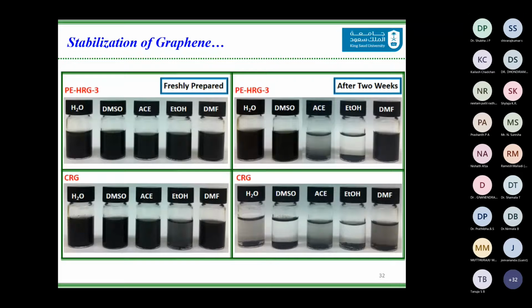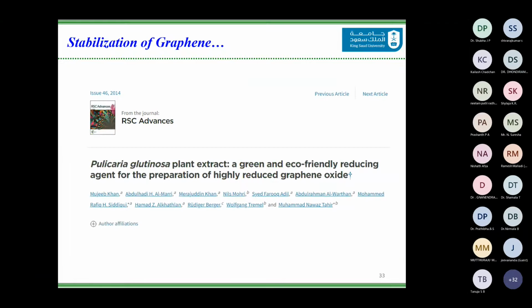Again, we studied the stabilization of graphene. This time we used the plant extract obtained graphene, dispersed it in various solvents, and compared it with chemically reduced graphene. We found that the plant extract obtained highly reduced graphene is very much stable in water, in DMSO and in DMF, while the chemically reduced graphene is not stable in any of these solutions after just 2 weeks. So the stability of this graphene is very high and it can be used for various other purposes. This is where we published this paper.